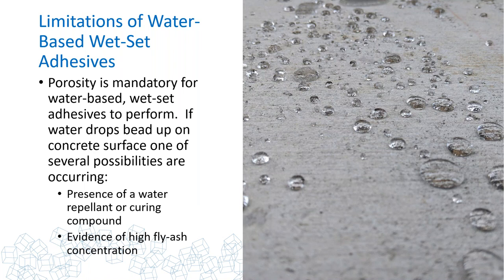There is an ASTM F3191 test method for determining the porosity of a concrete slab. You must do this in order to determine whether the water drops are going to go into the slab or not. They look like what you see on the right, and water's not going into the concrete at all. This is not something you can use a wet set on. You've got to remediate the situation one way or another. What's going on here? It could be the presence of a water repellent, silicate treatments that prevent water from getting into the concrete slab at all, or perhaps a high fly ash concentration as well can have some impact on how that water absorbs.